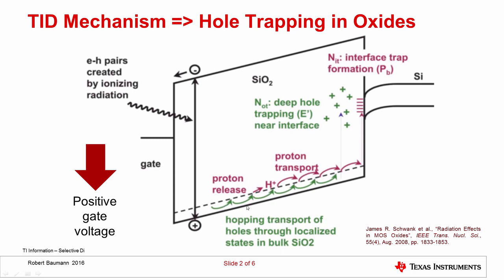Another feature of hole hopping transport is that since it disturbs the local crystal structure — particularly in gate oxides, which contain protons or ionized hydrogen — when the hole passes near a hydrogen site, the hydrogen is very frequently freed by the presence of the hole. So now you have holes moving by a hopping mechanism, and as they hop, they actually release hydrogen ions or protons into the gate oxide. Since we have an electric field, the positive charge on the gate pushes both the holes and the positively charged protons towards the interface.